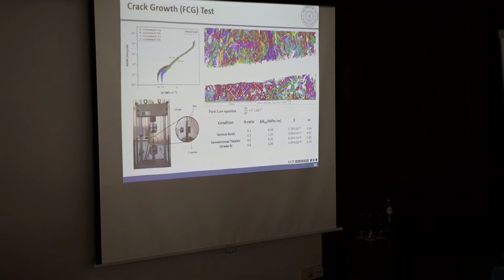Then we did fatigue crack growth analysis at two different R ratios, 0.1 and 0.5, and it is tabulated here. We obtained a threshold of 4.1 and 4.7, and we even tried grade 5, that is the conventional Ti-6-4, and in this case we have around 4.25. So we are able to obtain a threshold near to the conventional one.